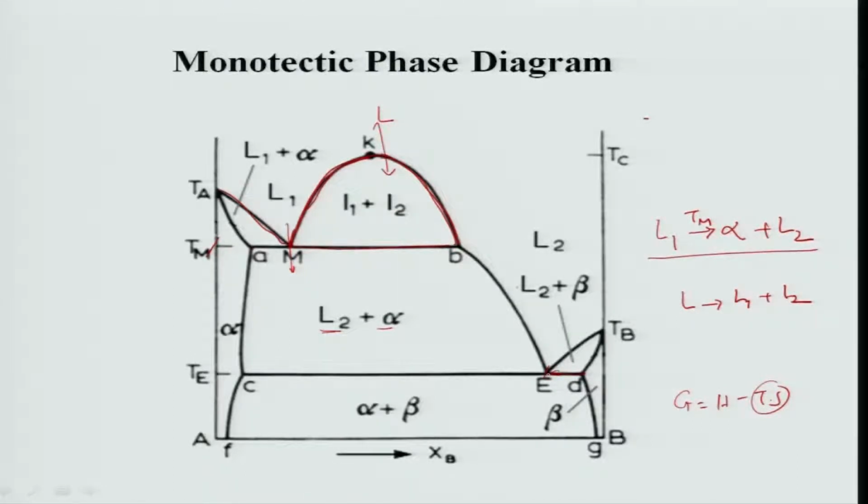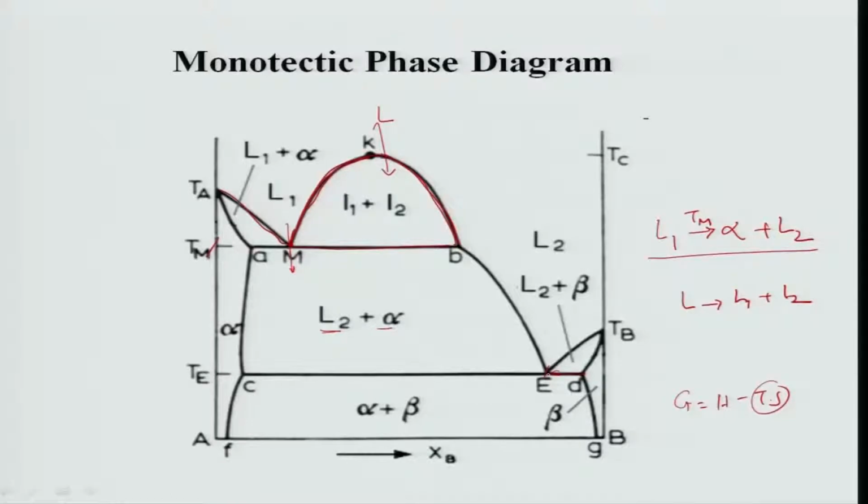For the copper-lead system, the eutectic point is 99.94% of lead. So, therefore, alpha copper is very small in the eutectic. It is basically a divorced type of eutectic in which beta is very large, alpha is very small. Okay. So, let us now discuss further. As you see here, we have got three important things happening in this phase diagram, which I list on the right side of this slide.